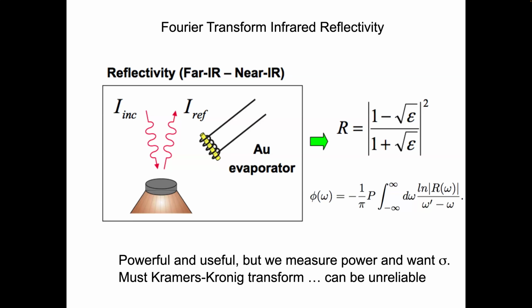We're physicists who want our complex response function. So how do we measure just the reflectivity, which is a magnitude, when we want the complex response? We can't get that just from this because this is an absolute value squared. So just as there are Kramers-Kronig relations for the sigma 1 and sigma 2, or dielectric constant, complex response, there is a Kramers-Kronig relation between the magnitude of the reflectivity and the phase that comes in from the natural log of the reflectivity. Kramers-Kronig transformed in an appropriate fashion is the reflected phase. And so this is how this is done.